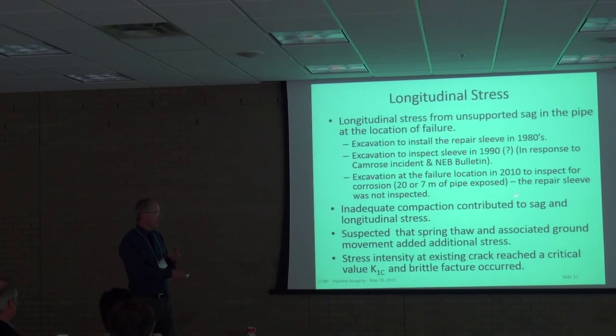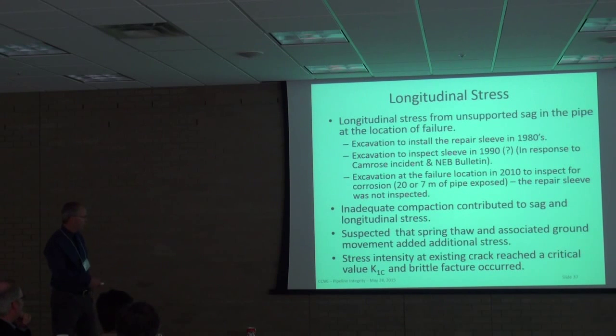But they didn't do any additional NDT on it. They didn't go back, and no one understood or remembered this NDT bulletin. So no one went back and looked at it. And same as the other example I showed you, as a result of having dug up this line, you've got this compaction, now you bury it again, and then the soil starts to settle with additional stress. They also felt that there was some additional stress put on it due to the spring thaw and associated ground movement. And so eventually, at this existing crack that had been there for 25 years, digging it up and disturbing the ground resulted in additional stress to reach the stress intensity factor, and then brittle fracture occurred.